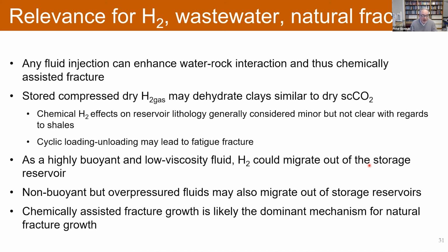There's also the effect of cyclic loading. This is not something we have for CO2. You just inject once. But for natural gas and hydrogen gas, you would be injecting, producing, and that causes load, unload cycles that may also enhance fracture growth. It's a fairly universal issue to deal with. Hydrogen may be less reactive than the CO2, but in detail, this needs to be looked into.